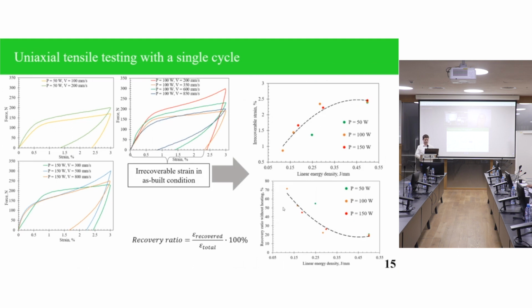Right. Do you have any idea of what the modulus would be that you measured? Sorry, I didn't hear. Repeat. Do you have any idea of the physical values of the modulus that would result from your measurements? Yes. So for austenite, the modulus is 40 GPa, and for martensite phase, as I remember, it's lower. It's about 10. So for different samples, I received slightly different results in between these values. But I didn't put emphasis on the elastic modulus in this study because I was mostly interested in irrecoverable strain after the single cycle deformation of these samples.